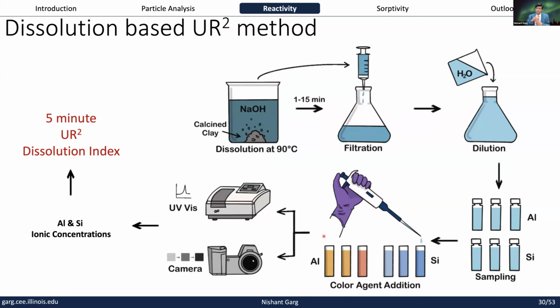But for us, for calcined clays, we catch them at 5 minutes. For another material, for example fly ashes, we're actually seeing maybe 15 minutes is better than 5 minutes because it's a little bit slower reacting. So the time may change, and somebody could even change the temperature or the alkalinity. The whole idea is you can play with all these different things. The end goal really depends on what you're trying to predict. For us, we're trying to predict the R3 as well as the SCI, and it's just an optimization game of where we catch. So we change the time, but we keep the dissolution conditions constant, because that's what has been working for us so far.